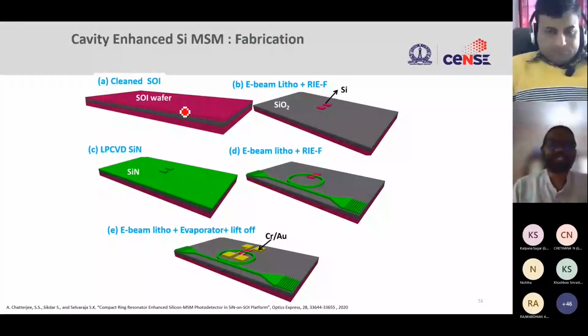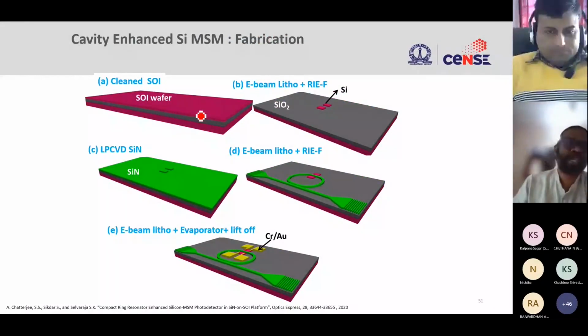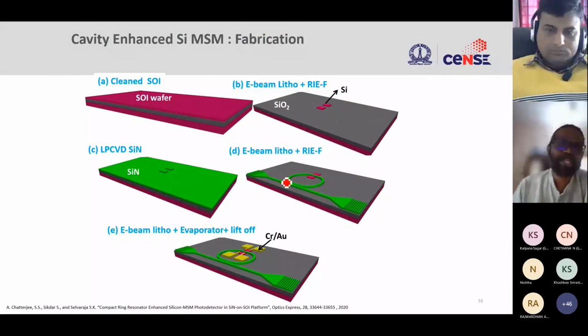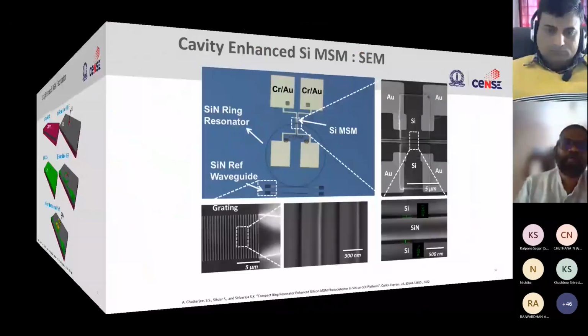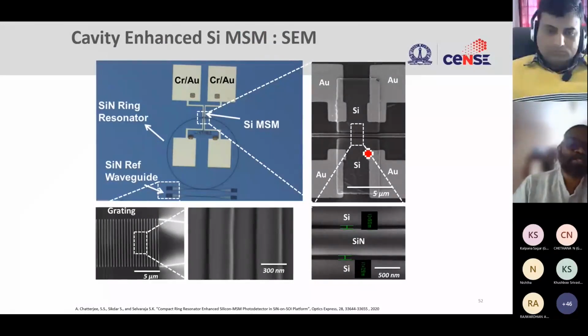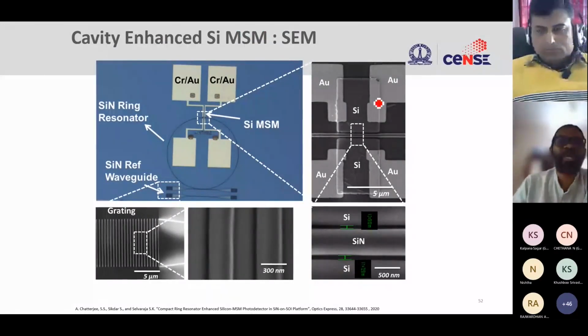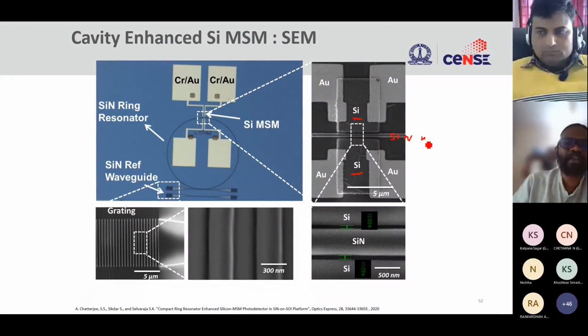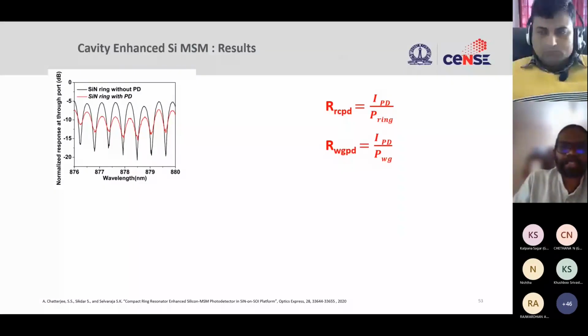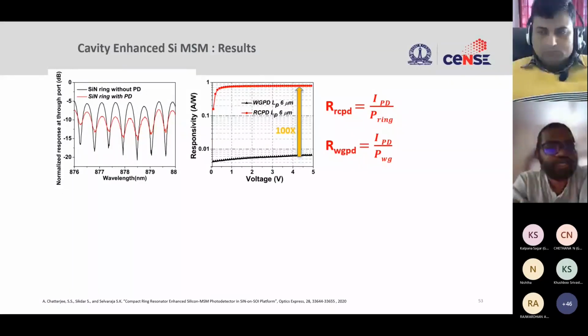So we fabricated this kind of proposal, where we have this SOI, we have the silicon, and we put this nitride and so on. And this is how it looks. This is the scanning electron microscope image of the silicon detector that is sitting on either side of your silicon nitride waveguide. So we have this waveguide, and then we should be able to take the light out, get it absorbed, and then collect the charges out. And this is what we measured.